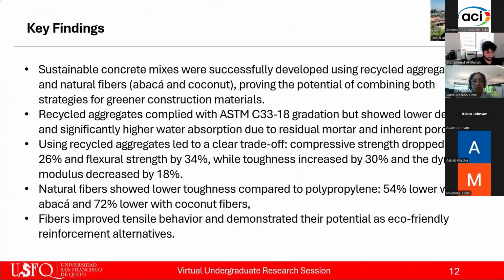Finally, the key findings. We developed sustainable concrete using recycled aggregates and natural fibers like abacá and coconut. Recycled aggregates boosted toughness by about 1/3, but lowered the dynamic modulus by nearly 1/5. On the strength side, they reduced compressive strength by roughly 1/4 and flexural strength by about a third.